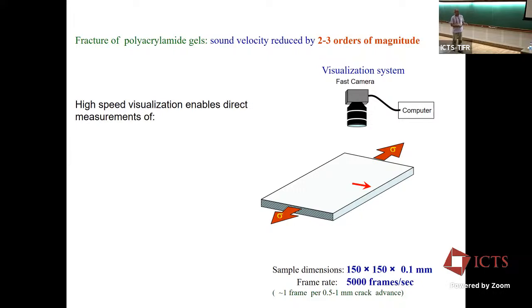This is a schematic of the experiment. You have a thin plate, a sheet of this Jello, which we molded. You illuminate it from the bottom and look through a fast camera. So immediately you can see the crack tip as it's moving. You can measure the parabolic structure at its tip.